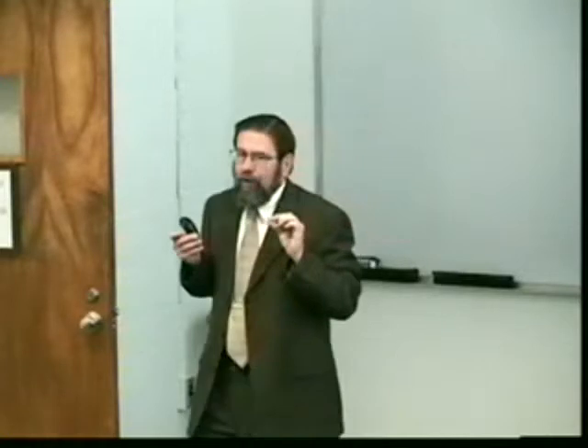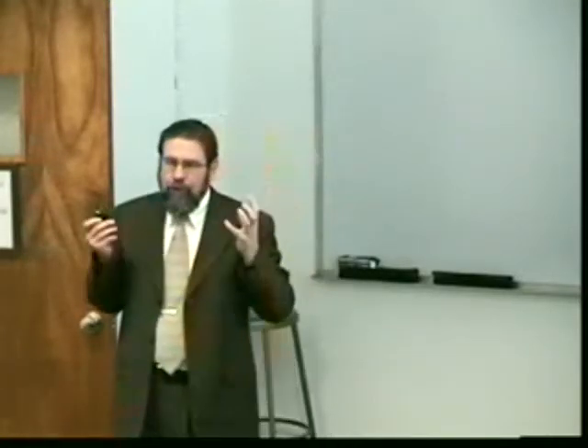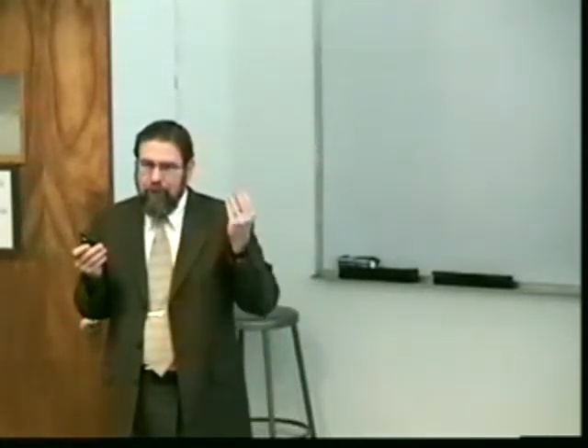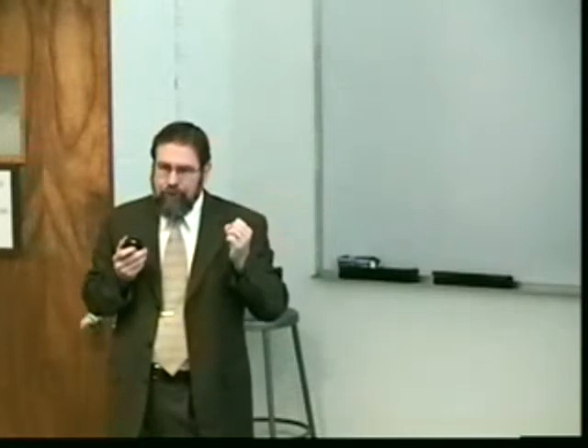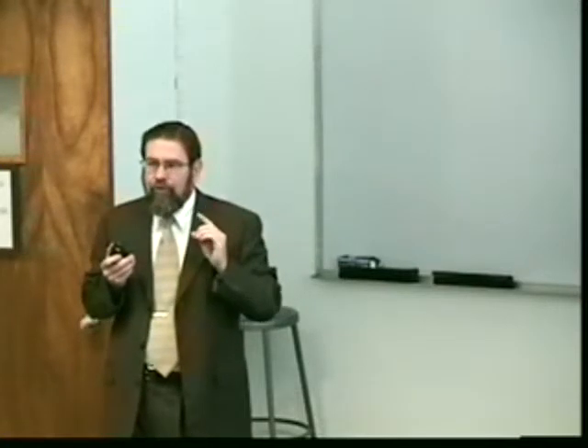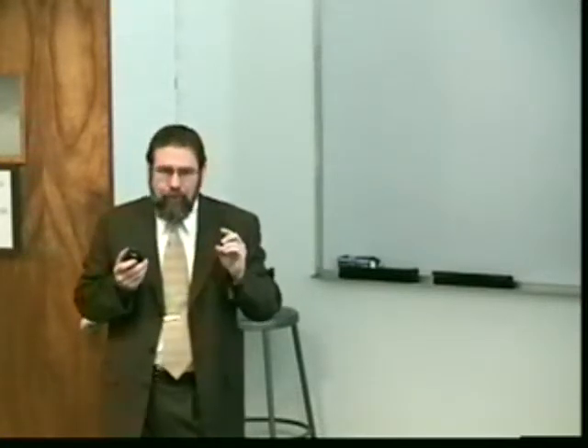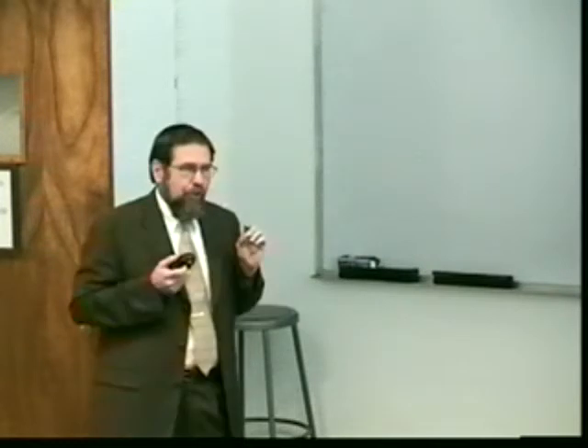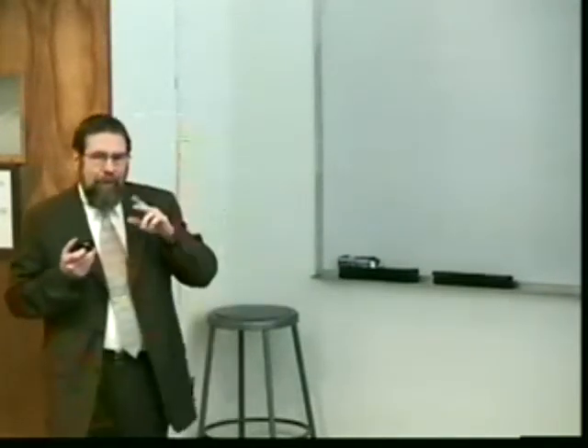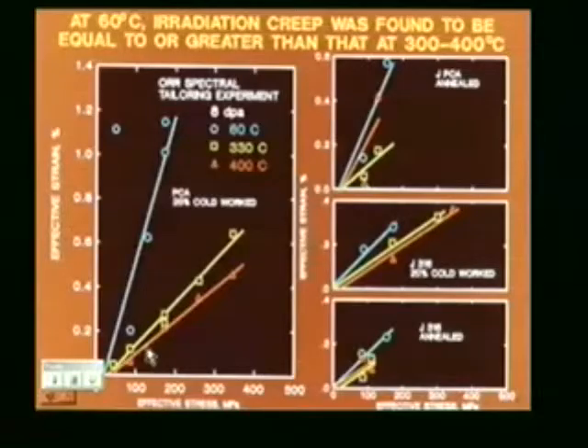And what's happening here at these low temperatures, interstitials are free to diffuse throughout the lattice and can be attracted to the dislocations. But the vacancies are frozen out. Temperature is too low for them to diffuse. So instead of having them balance, we have a preponderance of the interstitials, and that's causing a higher creep rate at the lower temperature. And we can even get a radiation creep at liquid nitrogen temperature.